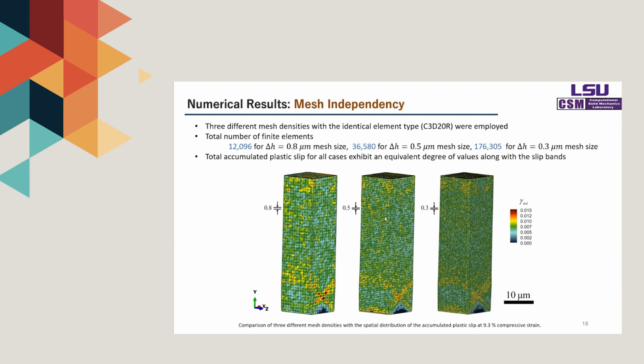And finally, for the fine mesh of DH 0.3 micrometer, we use 176,305 elements. The figures provide the 3-dimensional contour mappings of the total accumulated plastic slip with different mesh sizes at 9.3 compressive strain.